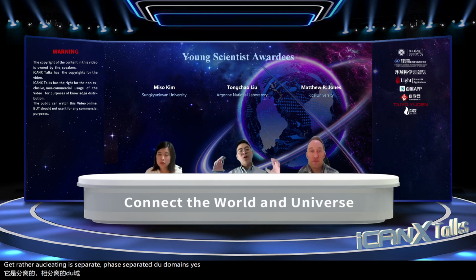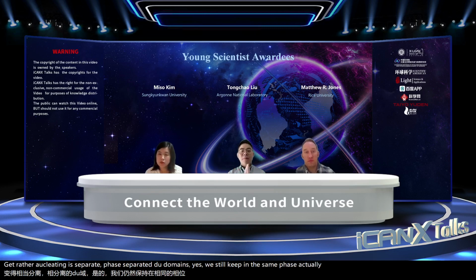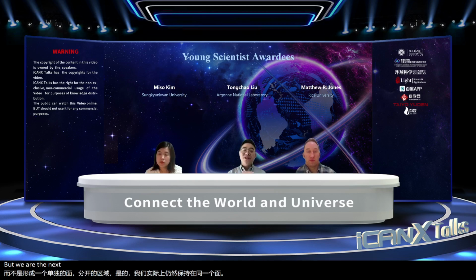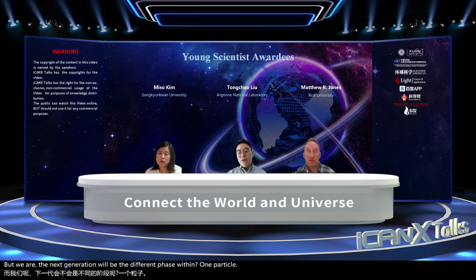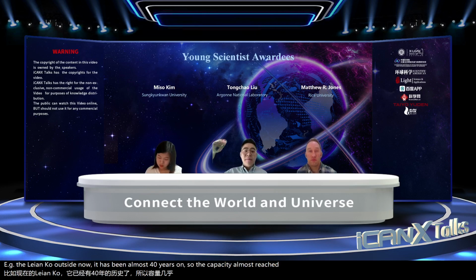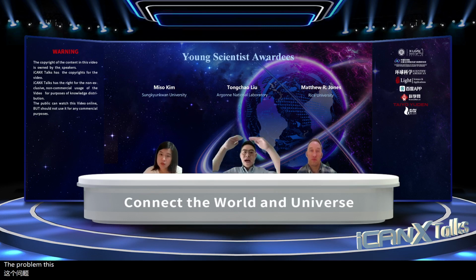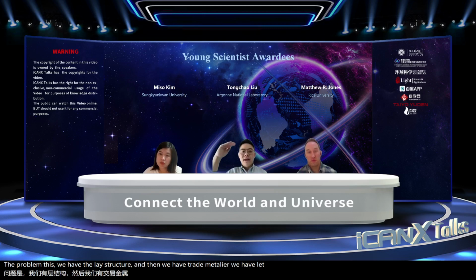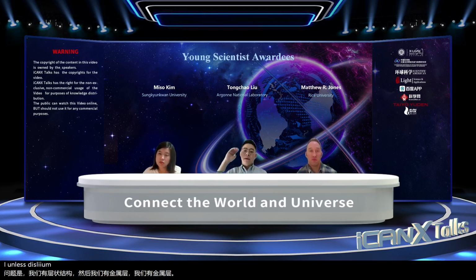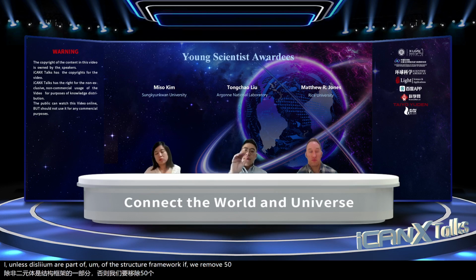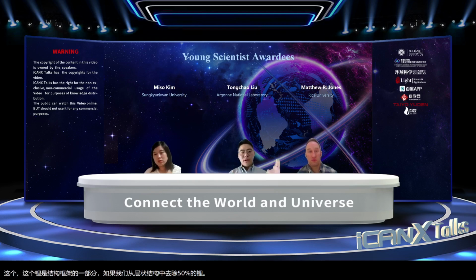Yes, we still keep in the same phase actually, but the next generation will have a different phase within one particle. For example, the lithium cobalt oxide has now been around almost 40 years, so the capacity has almost reached the maximum. The problem is this: we have the layer structure, with a transition metal layer and a lithium layer, and this lithium is part of the structure framework. If we remove 50% of the lithium from the layer structure, the structure is still very stable.